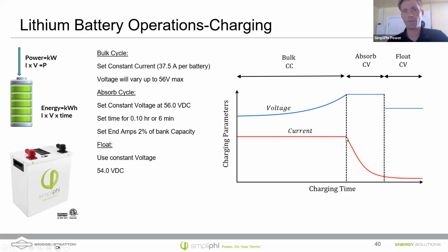Notice that the current is just flatlined at a constant value here. That's the bulk cycle. Now, if you had 2 batteries, you would double that 37.5 for 75. If you have 10 batteries in parallel, it would be times 10. So you could charge 10 of these batteries at 375 amps. But that's done at a constant current. Now, as long as your charging equipment can maintain that current, so if you're running off of solar and it's not able to produce that full current, it will charge as fast as it can up to that limit at a constant current. But notice, as we start to charge a battery up, the voltage that we have to apply to charge that battery starts to rise, right?